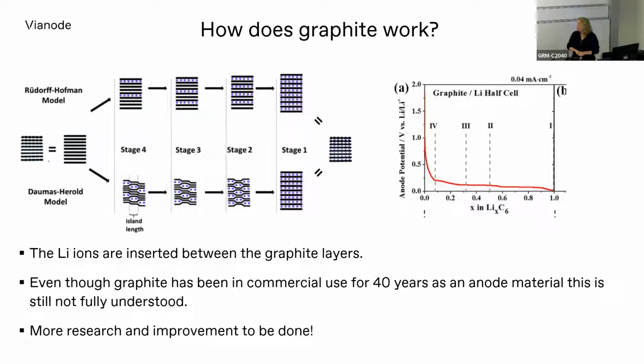So then if we talk about graphite, how does it work? This is important for understanding why graphite is the dominant anode material and why we expect it to continue to be the dominant anode material into the future. So when you charge the lithium ions into the graphite, what happens is graphite is a series of layers of graphite in hexagons that are long sheets. And then between them, you only have van der Waals bonding, so very light bonding. And it's quite easy for those sheets to separate just a little bit.